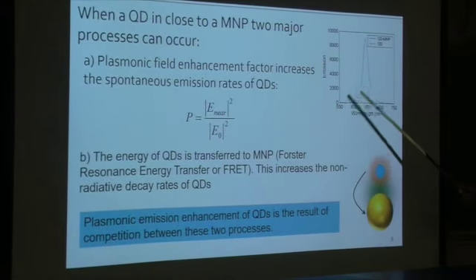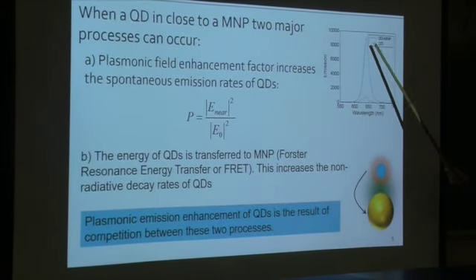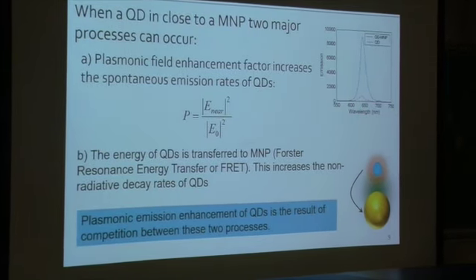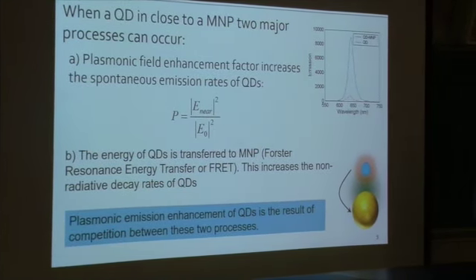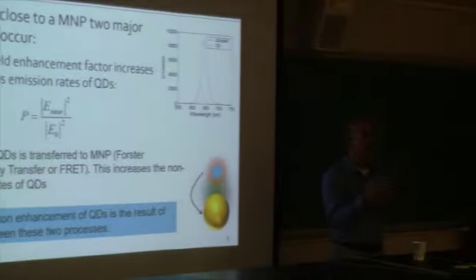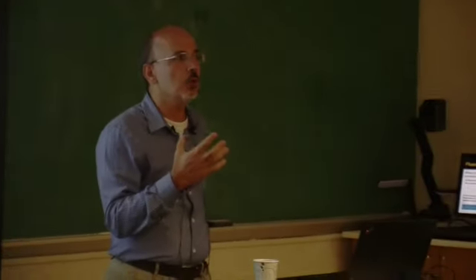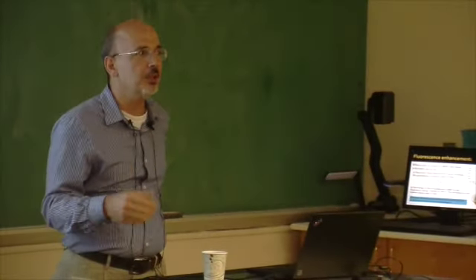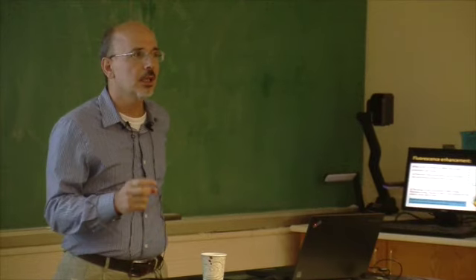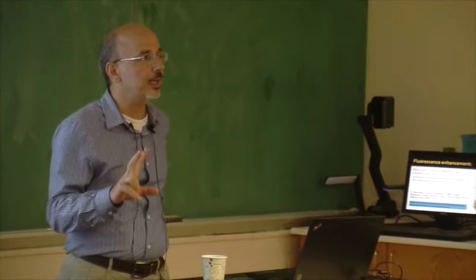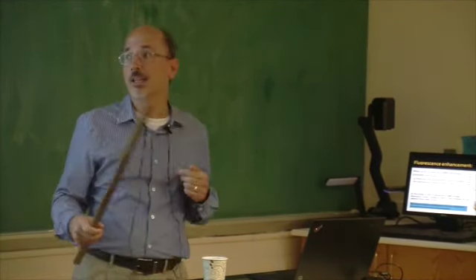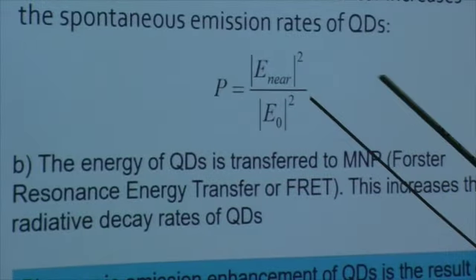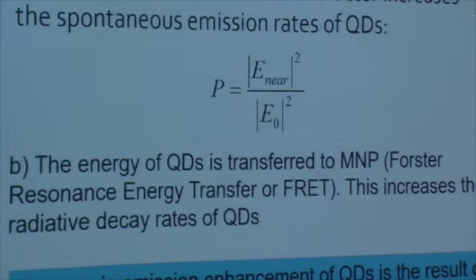If you ask how I can improve this, how I can enhance that emission, and of course, as I said, if you deal with the defect, reduce the defect. But if you don't, you want to design your material to do that, you have to consider two facts. The first fact is, as I said, the field enhancement factor that I mentioned.